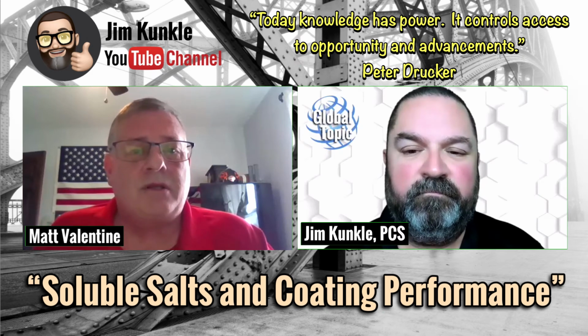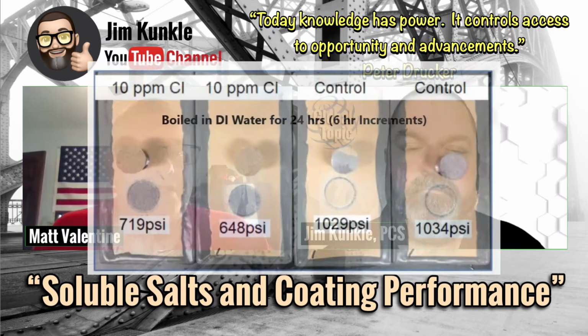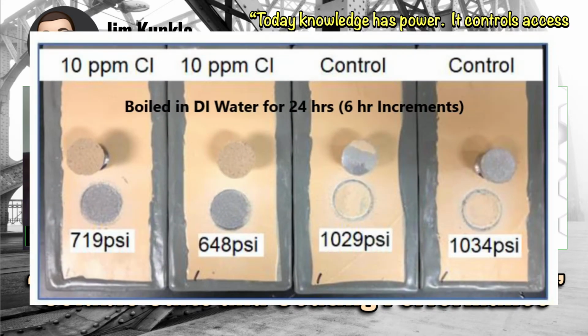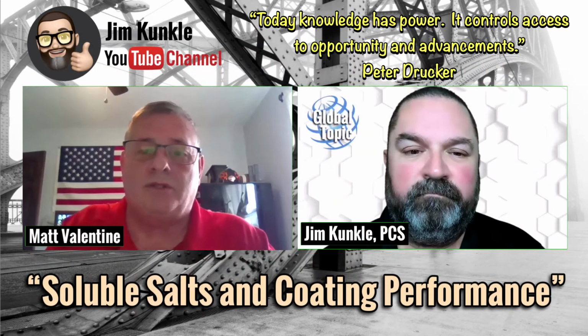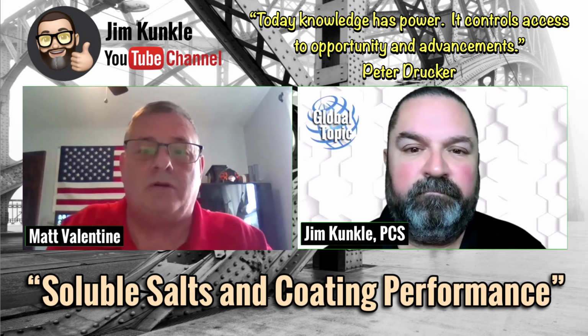And the dollies for the 10 ppms, the adhesion rating on the one panel was 719. The other panel was 648 psi. That was what it took to get bare substrate failure. Then our control, we did the same testing on that. And we had psi ratings on the one coupon at 1,029 and the other one at 1,034. And it was just the coating system still adhered to the steel.